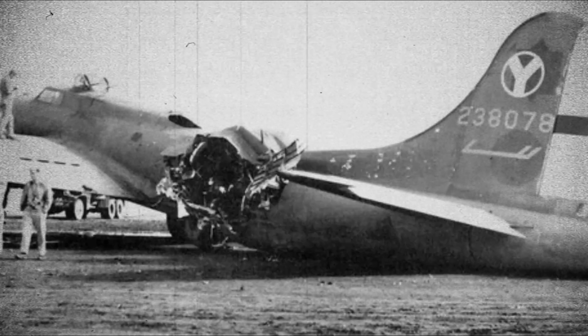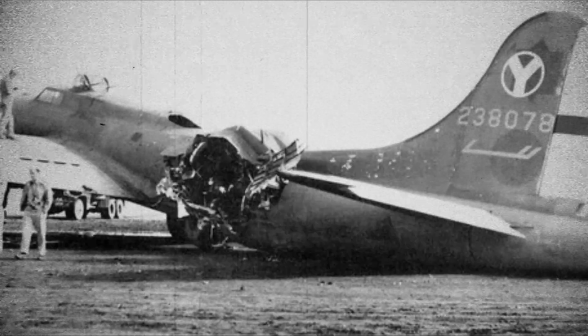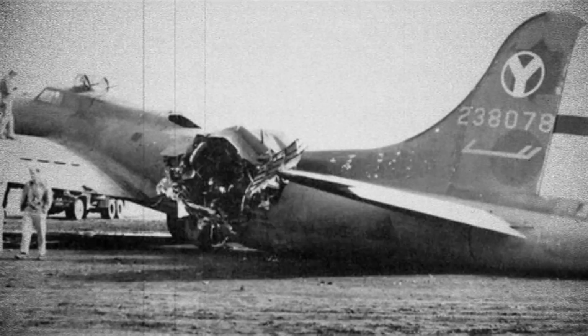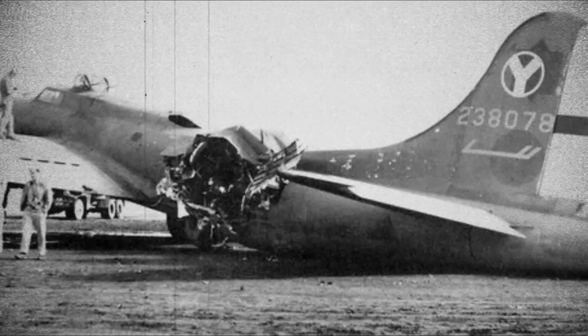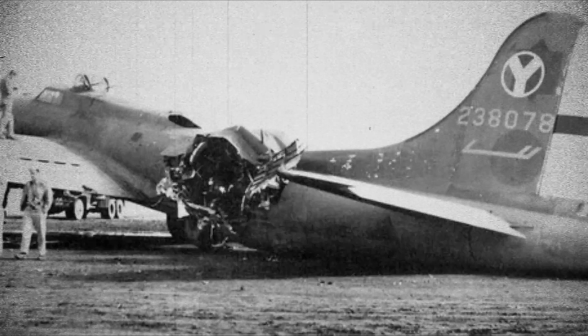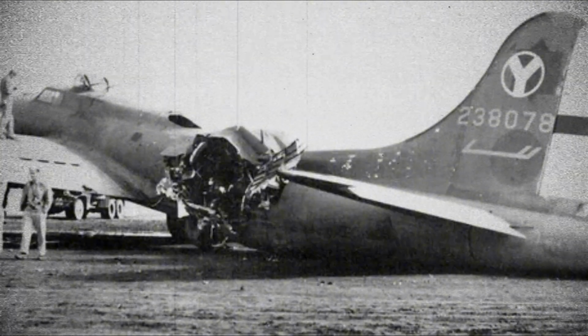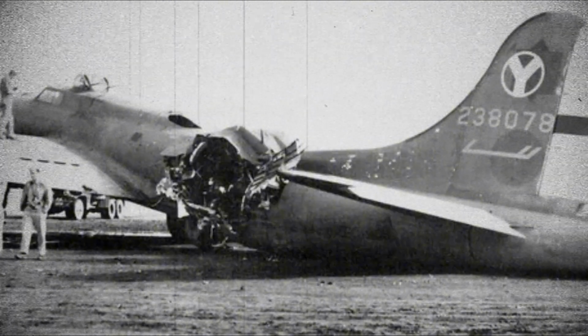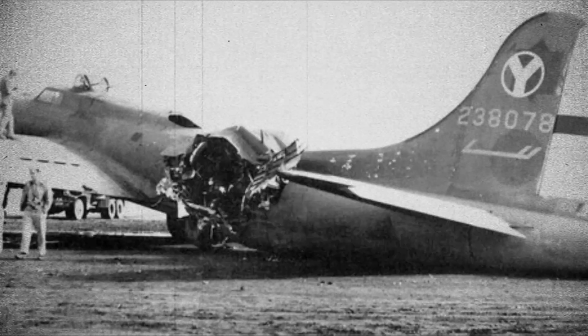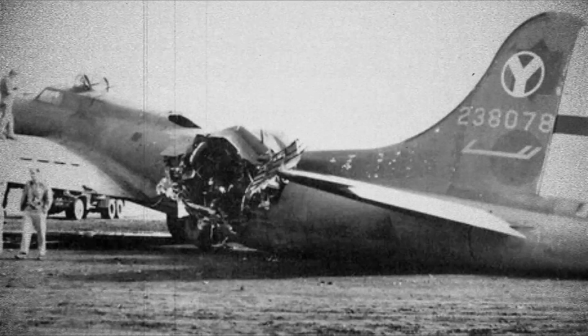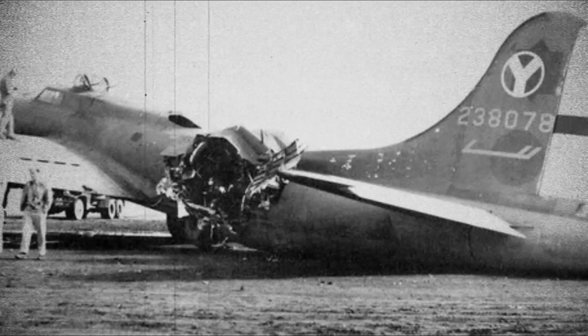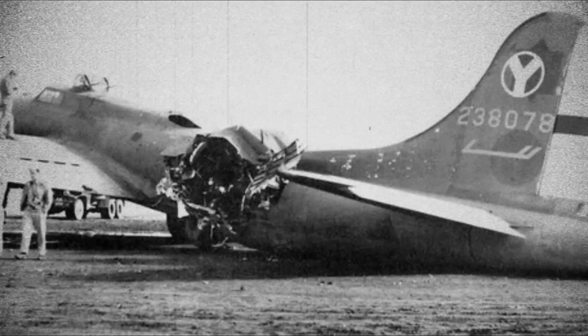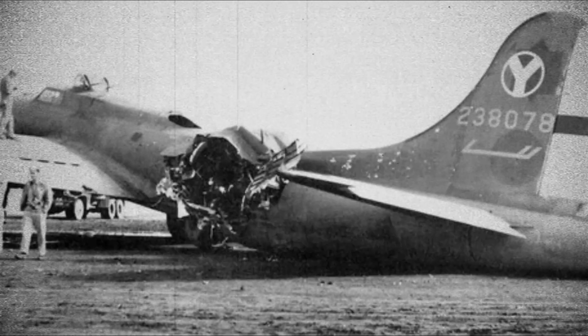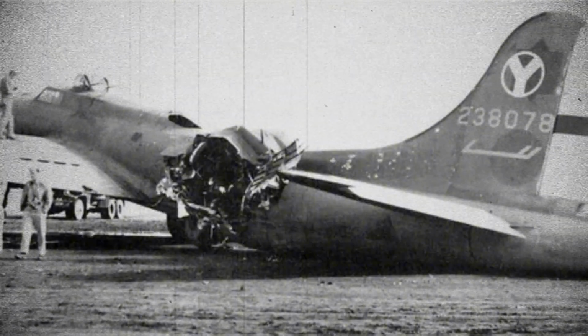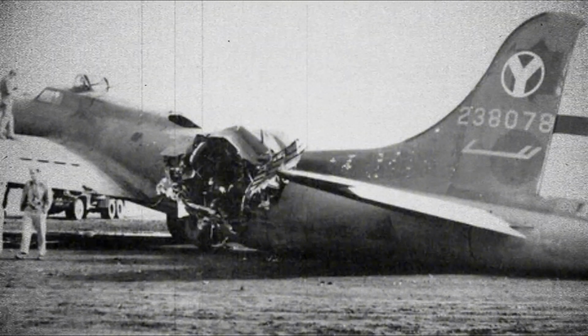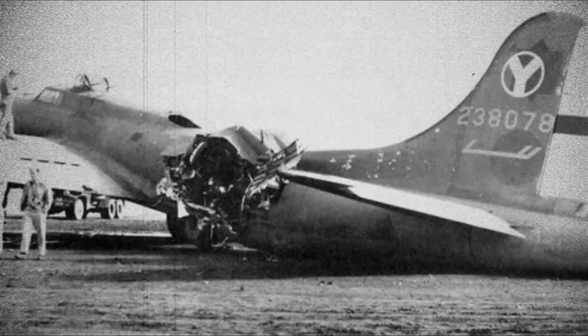Medical examination after landing revealed that the fragment, which weighed approximately 0.8 ounces and came from a proximity-fused shell that detonated near his aircraft, had penetrated the outer fabric layer, struck the first steel plate, cracked it partially, then struck the second plate, which stopped it completely. The cracked first plate absorbed most impact energy through fracture propagation, while the second plate, slightly offset from the crack location due to the overlapping arrangement, provided backup protection. Without the two-layer system, the fragment would have penetrated Mueller's chest cavity and caused fatal injuries to his heart or lungs.